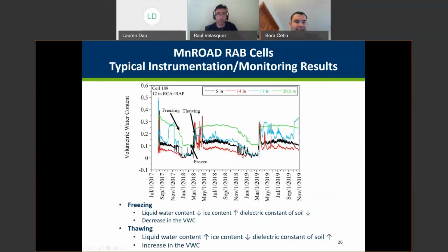Thank you, Raul. And we will talk a little bit about the type of data that we collected within the base layers in terms of volumetric water content and thermocouples. Here is one of the slides that shows how the volumetric water content changes at 5-inch, 14-inch, 17-inch, and 20.5 inches depth from the ground surface. In the test section that we have 12-inch thick RCA RAP mixtures. And as you can see, at each depth we see how the volumetric water content changes over time.